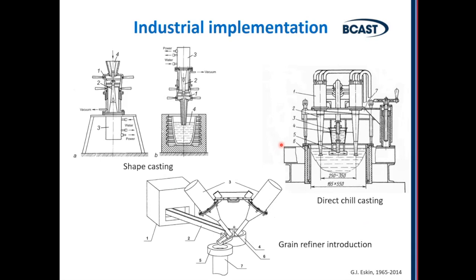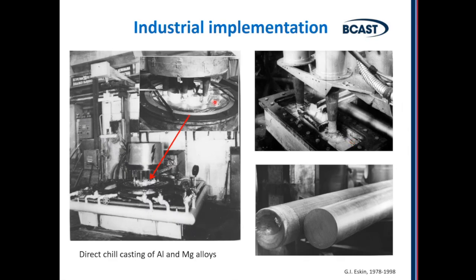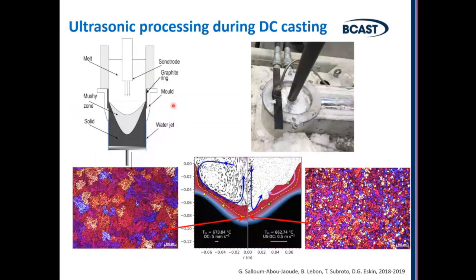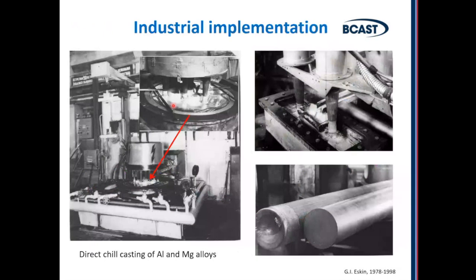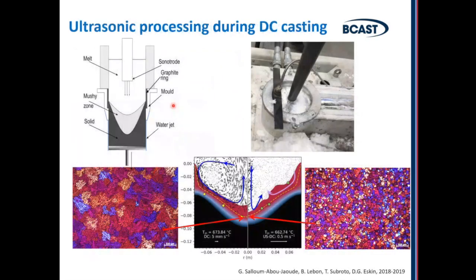There are a lot of schemes of practical implementation of ultrasonic processing in shape casting and direct chill casting. So these are examples of direct chill casting for aluminum alloys with multiple sources of ultrasound in large molds. We work a lot on this in terms of technology development, and here there were basic principles known and the results were achieved. Now we know much better about what happens inside via modeling. We know how cavitation and ultrasonic processing change the shape of the sump of the billet, change the distribution of alloying elements, how flows are arranged and so on, and that helps us to optimize the processes.